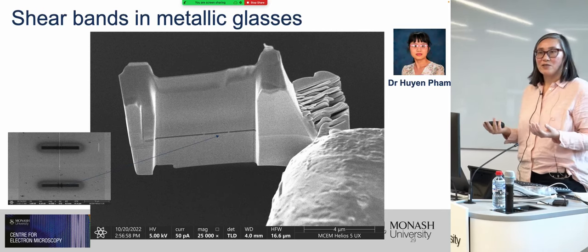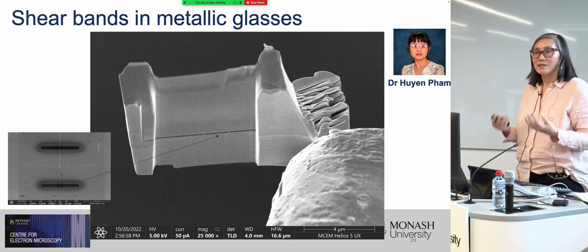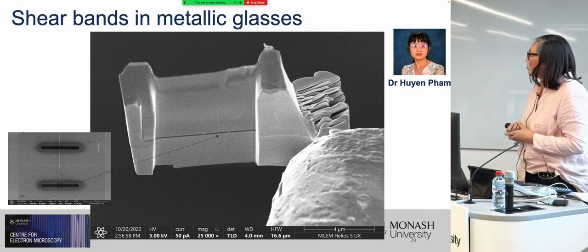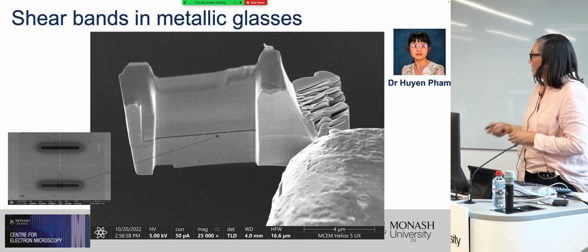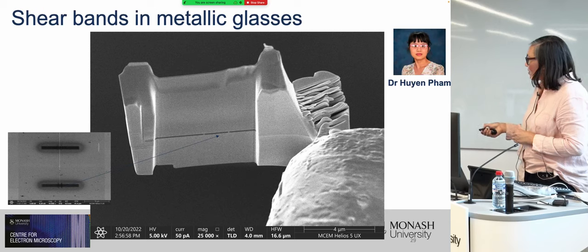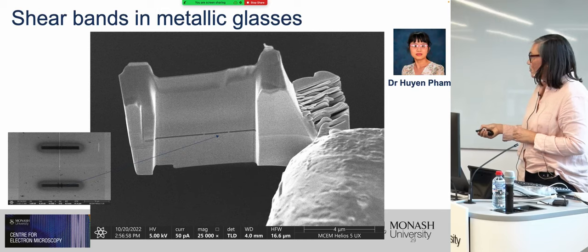So we're actually trying to look at similar structures in a shear band in a metallic glass, and we're using Monash's new FibSEM to do it. So here you can see the surface of a metallic glass, where we get a little bit of contrast from the shear step marking out a shear band in the glass.